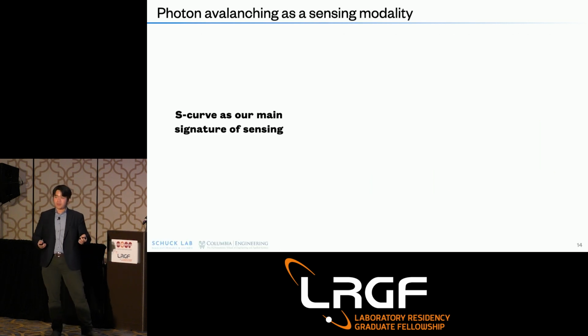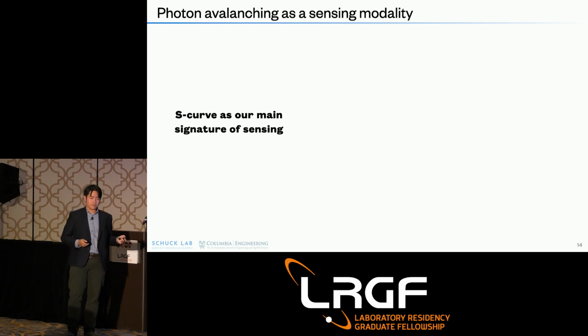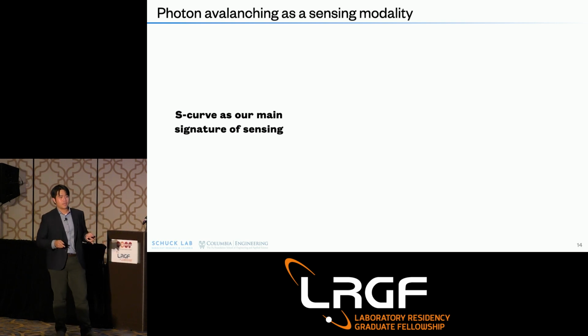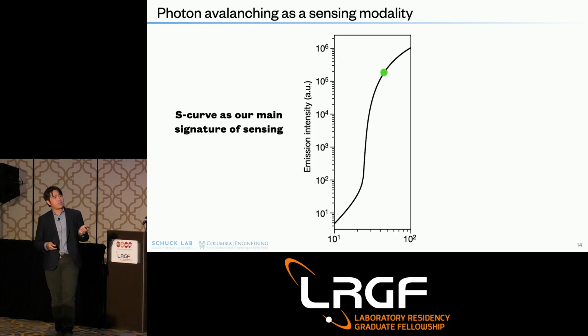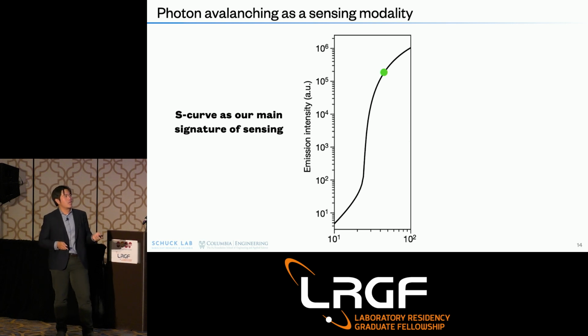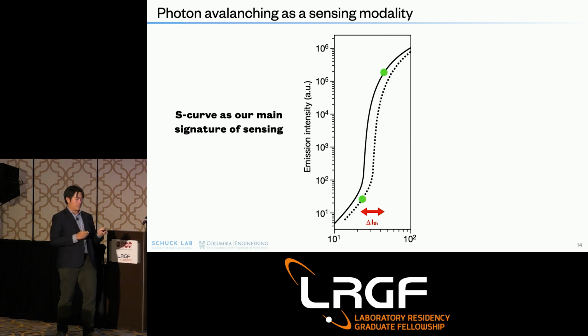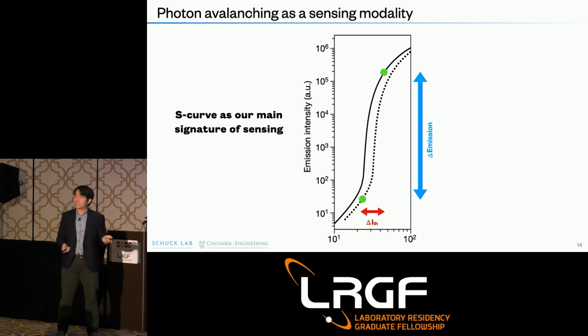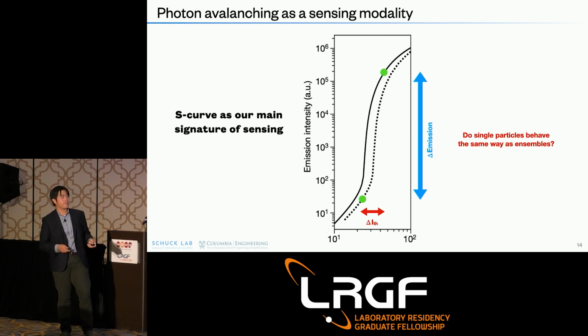Now, this is all exciting because for a spectroscopist, we not only get to measure and study lanthanides, we can also use this S-curve as a signature of sensing. So if you have a lanthanide ion or a nanoparticle sitting in some space, and you perturb it to such a point that the avalanching threshold shifts by a little bit, what you get is a very large change in your emission in general. So this by itself is a potential source of sensing in this material.